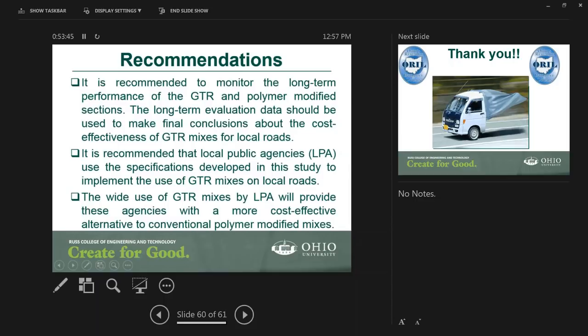We have developed a mix design specification for GTR mixes to be used by local public agencies. So local public agencies that want to use the GTR mixes, we recommend that they check those specifications when trying to use such mixes. And again, if the GTR mixes are widely used, then we can see that they have a lot of benefits and they can be more cost effective as compared to the conventional polymer modified mixes.